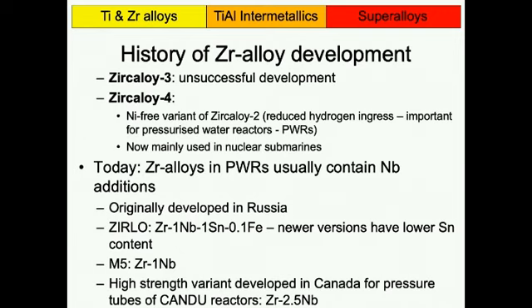The only case where we actually have a high strength variant is for the Canadian CANDU reactor, and that is a heavy water reactor which works with uranium fuel, which is actually not enriched. And there they don't have a pressure vessel, but they have pressure tubes. And those pressure tubes are made from zirconium, and because it's pressure, they need to sustain higher strength. And so the alloy used there is Zirc 2.5 niobium. But that's really the only alloy which is high strength. The Canadians have looked at some alloys to replace this, but actually they're still with that alloy, Zirc 2.5 niobium.